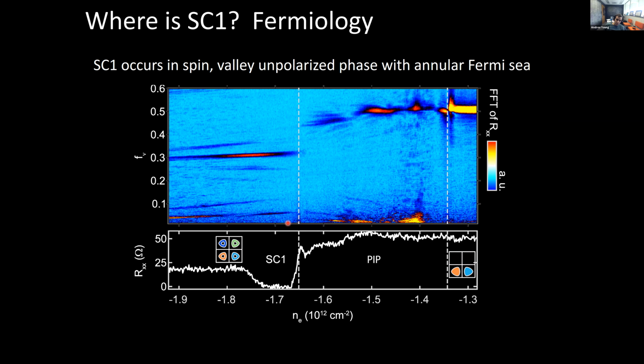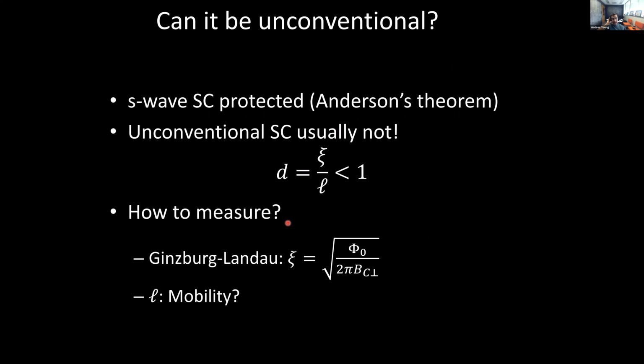One of the features of most, if not all, electron-mediated superconductors is they typically don't have conventional pairing symmetry. In particular, they're often not S-wave. In the cuprates, they're D-wave. And in many theories, you'll end up with other types of unconventional pairing symmetry. And a key fact about superconductivity in its conventional form is that when you have an S-wave superconductor, disorder doesn't really matter, because the Fermi surface is uniformly gapped, and so even scattering across the Fermi surface by very strong disorder, by Anderson's theorem, is not going to degrade Tc at all.